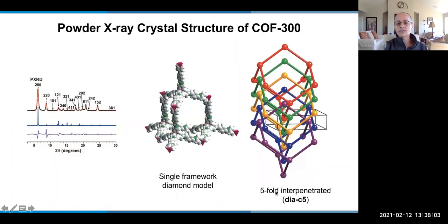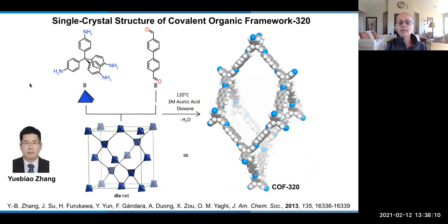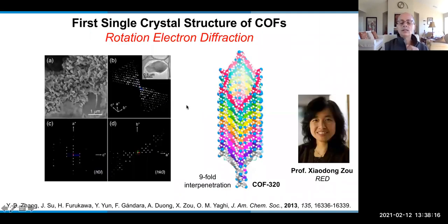The structure is 5-fold interpenetrated, we get from powder diffraction. And you can make the expanded version of this, but now with 3 molar acetic acid, okay? And it turns out this one, we are able to characterize with rotation electron diffraction. Single crystals of COF-320, where the characterization using the electron diffraction was done by Professor Xiaodong Zou.